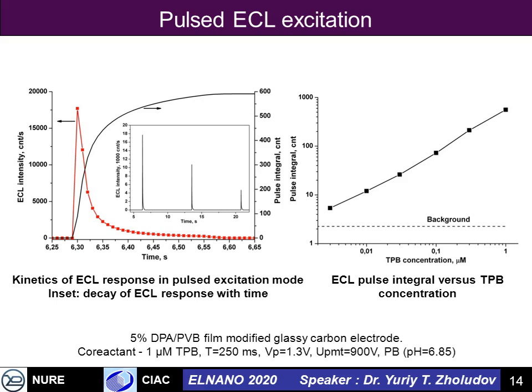Due to this high intensity in the pulse mode, it is possible to have very sensitive detection of our TPB coreactant, tetraphenylborate coreactant, using this film-modified electrode. It was found that the peak intensity is not so stable between the pulses, while the integral of light emission, which is given on the left image, black curve, is much more stable. So for measuring the capabilities of detecting the coreactant, the integral value of light emission during the pulse was used.